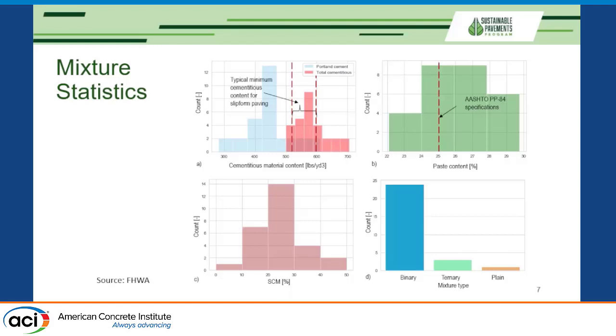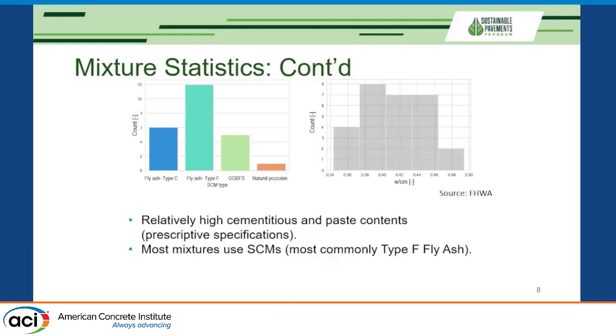Among our mixes, most of them are binary, meaning they have just one supplementary cementitious material. There are a few ternary mixes as well as one plain mix, and that one was from Hawaii because they don't have any SCM resources that are locally available. Finally, I am summarizing here the types of SCMs used in these mixes. As you can see, it's type F fly ash for the most part, type C fly ash, slag, as well as natural pozzolan, which was used in Nevada.